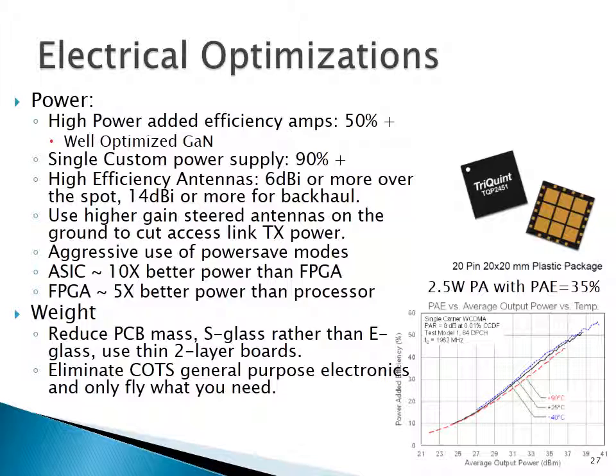So to do that, electrical optimizations that would be worth looking into would be very well optimized gallium nitride power amplifiers, because those amplifiers are going to be a major driver of your efficiency. TriQuint makes some that I found spec sheets for that looked all right, but that's 35, 36% efficiency at these temperature ranges. If you can find a way or work with a vendor to get up closer to 50% efficiency or better, that would be awesome. Power supplies are always an easy, low-hanging fruit, right? Just get rid of the commercial off-the-shelf power supplies and find a custom power solution, even if it's a bit heavy, that gives you 90% plus power conversion efficiencies.